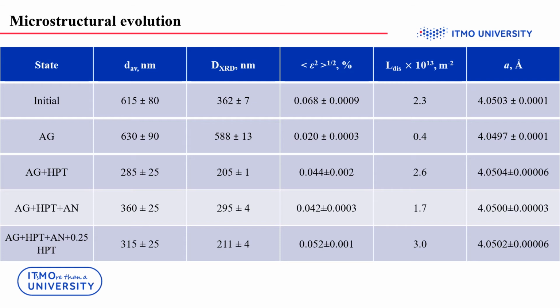In this regard, the obtained effect of plasticization can be well described by the physical model proposed by us earlier for commercial pure aluminum. According to this model, plastic deformation in UFG aluminum structured by HPT is carried out by the emission of lattice dislocations from triple junctions. The low plasticity in the state after short-term low-temperature annealing is explained by a decrease in the grain boundary dislocation density. As a consequence, an increased external stress is required for the emission of dislocations from grain boundaries, and a decreased number of lattice dislocations is emitted from grain boundaries.